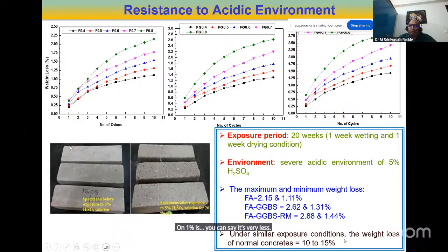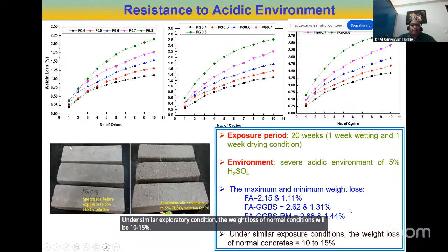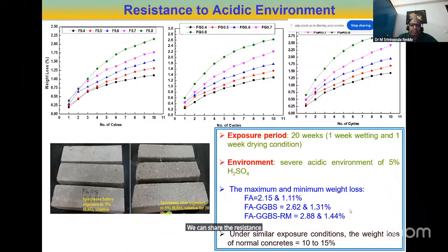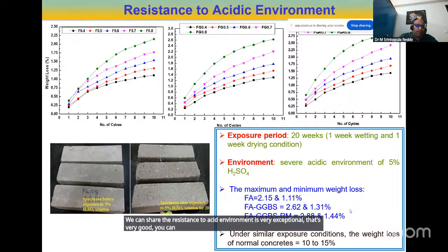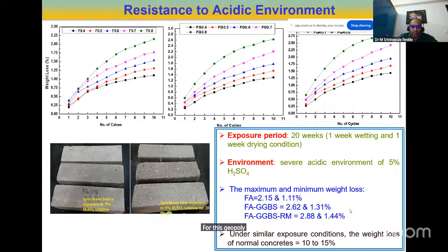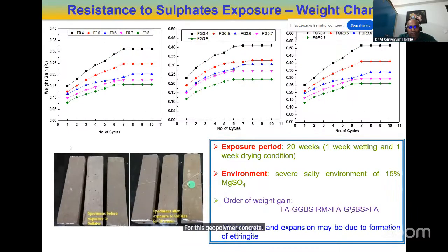Under similar exposure conditions, the weight loss of normal concrete will be 10 to 15%. We can say the resistance to acid environment is very exceptional, not just very good, we can say exceptional for these geopolymer concretes. Then sulfates also.